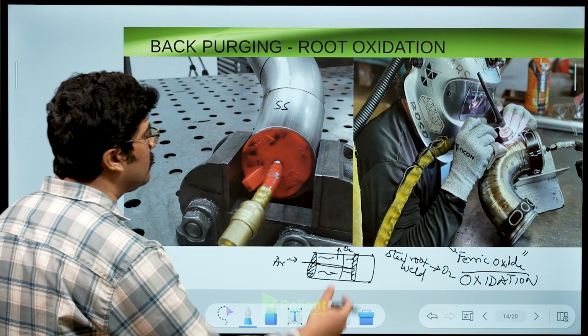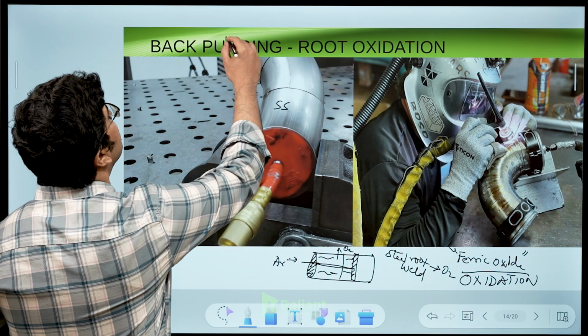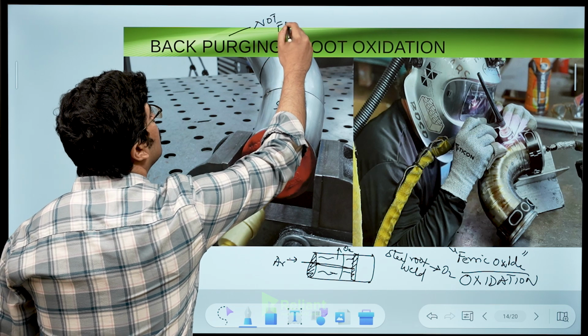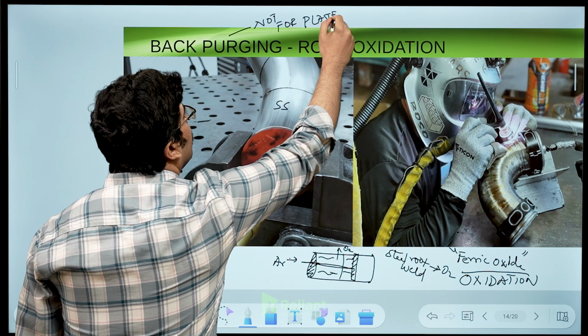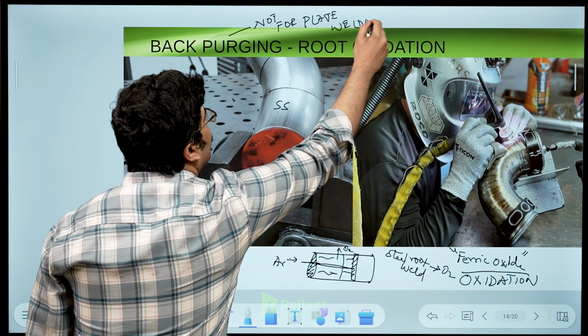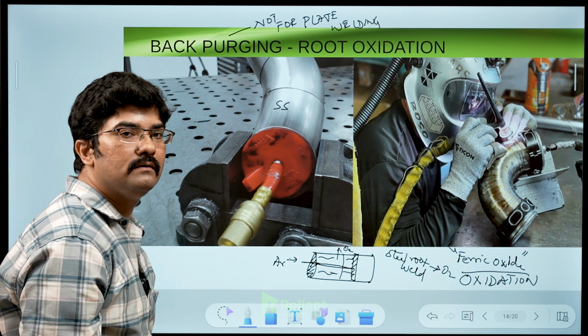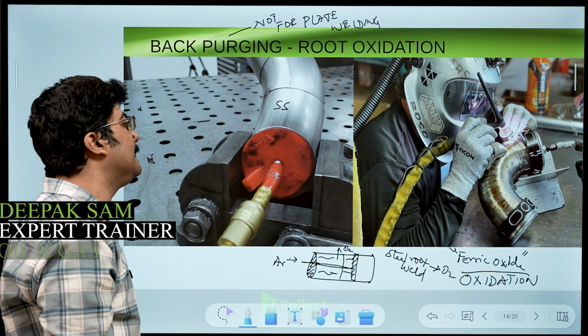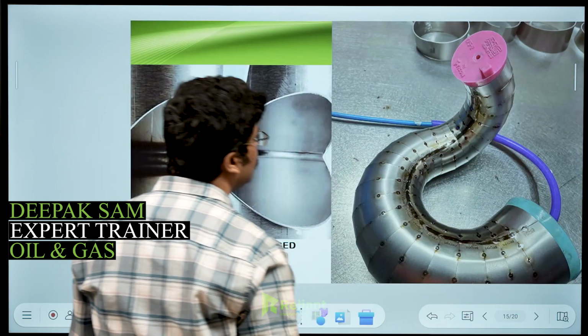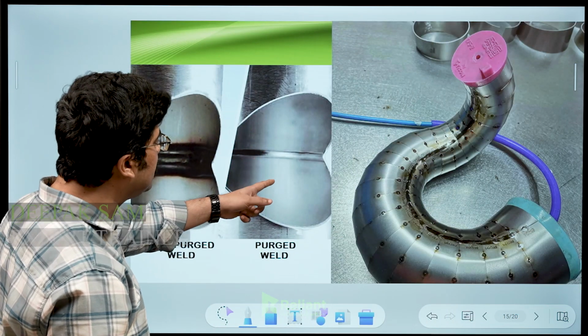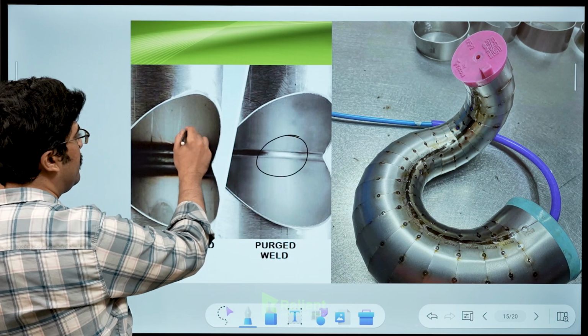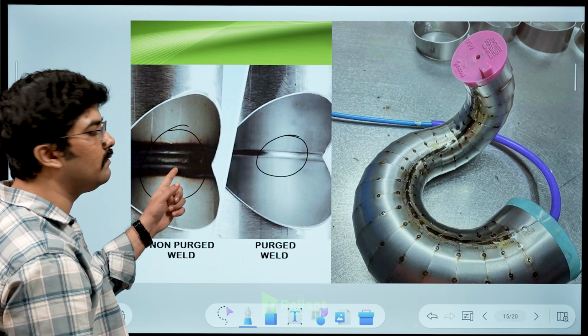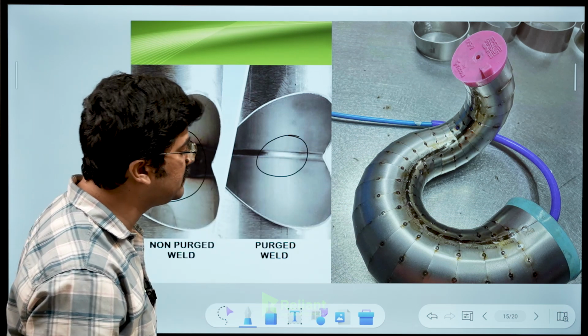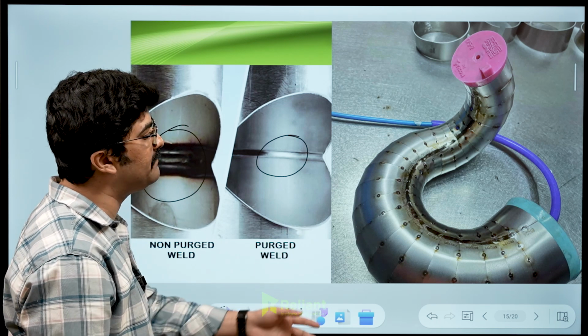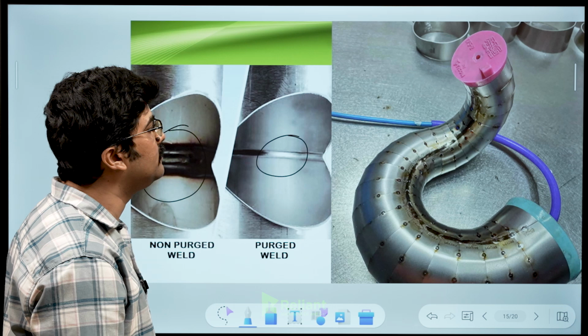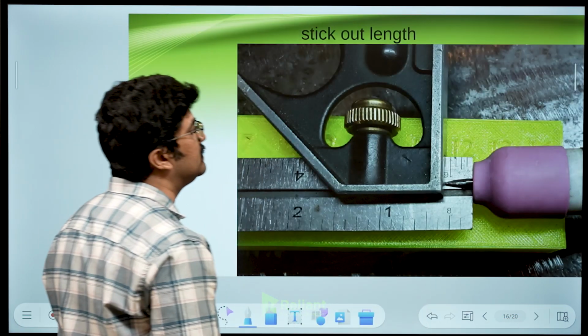So to avoid root oxidation, we use back purging. Back purging is not for plate welding, only for SS pipe welding. So you can see here, if you do the purging, you have a quality like this. If you don't do the purging, if you do the welding without purging, the quality will be like this. So mostly in stainless steel manufacturing, fabrication, pipeline construction, we do back purging when it comes to the TIG welding process.